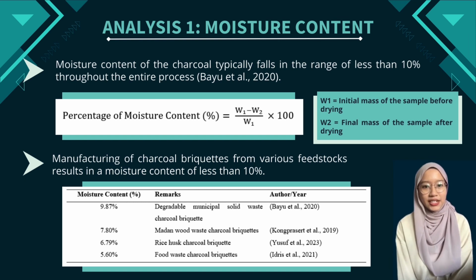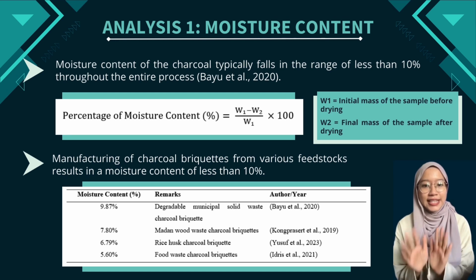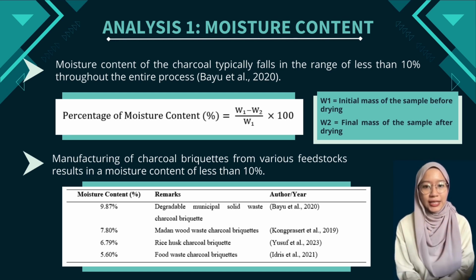In this research, there are 5 analyses to be considered. The first analysis focuses on the moisture content. Moisture content of the charcoal typically falls in the range of less than 10% throughout the entire process, based on previous research. This equation indicates the determination of percentage of moisture content, where the initial and final mass of the charcoal briquette sample will be considered. According to this table, manufacturing of charcoal briquettes from various feedstocks results in a moisture content of less than 10%, which may be deemed appropriate for use as charcoal briquettes.